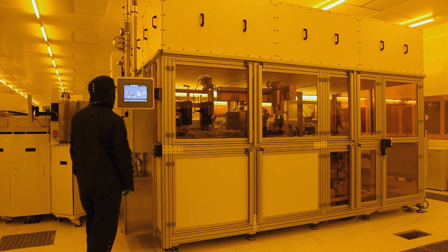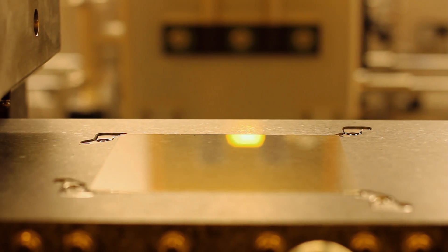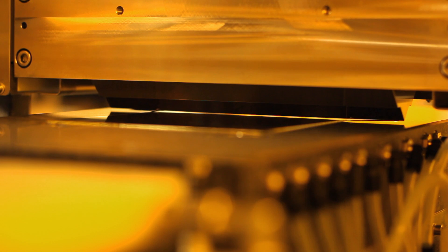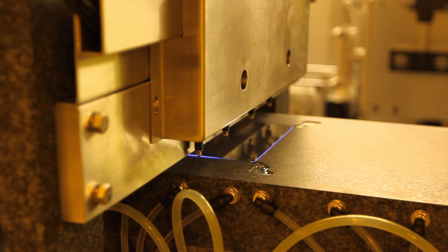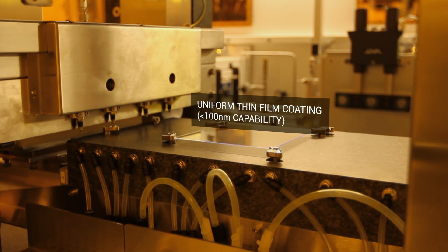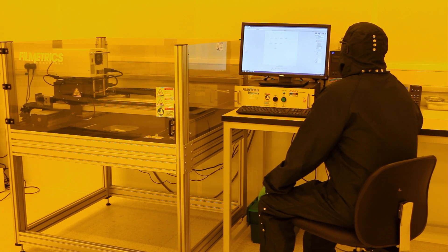The Ambient module has been designed to allow the solution coating of non-air-sensitive materials utilising a slot-die coating technique. Slot-die coating is a scalable thin-film coating process which provides an efficient use of materials in comparison to the more conventional spin-coating techniques employed for round substrates. Dry film thickness of less than 100 nm can be uniformly coated with this technique.